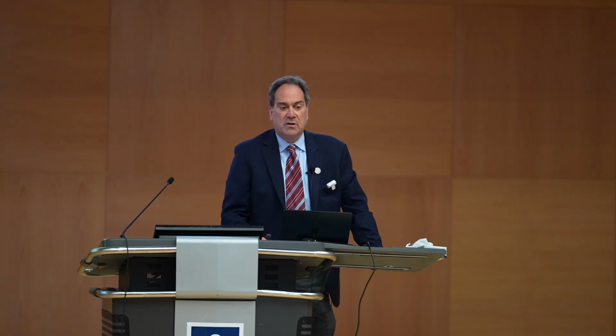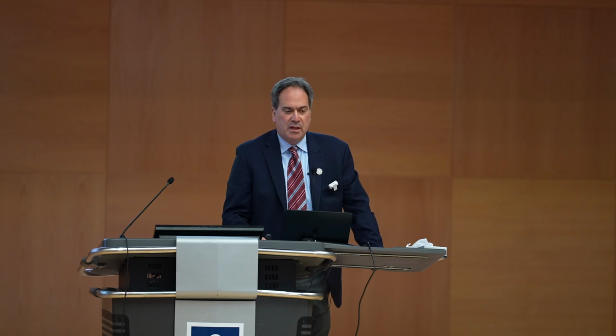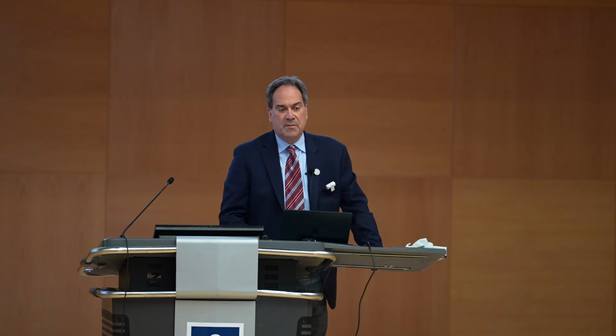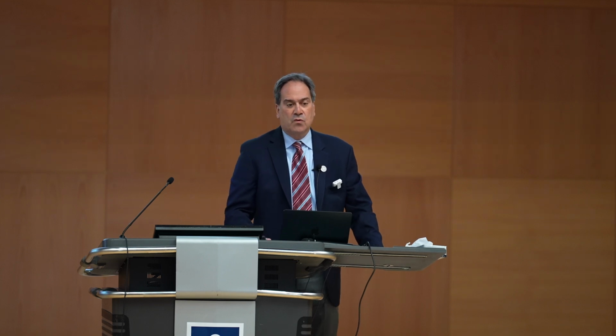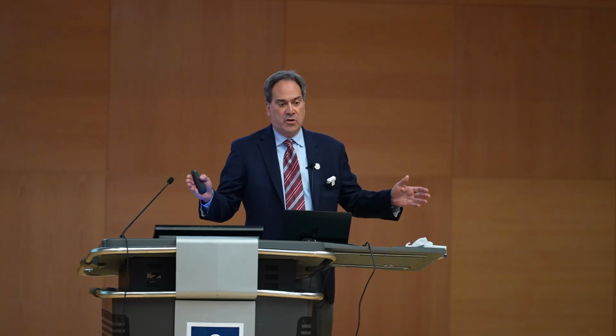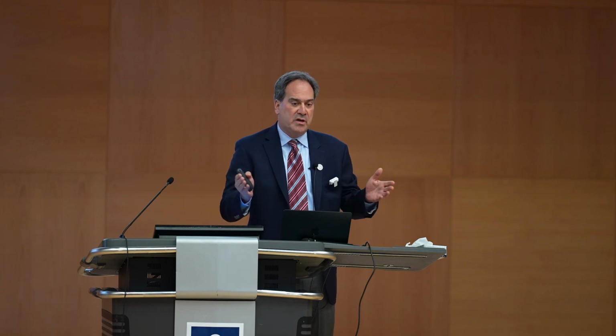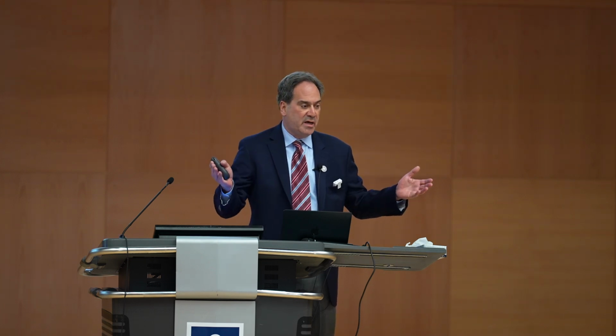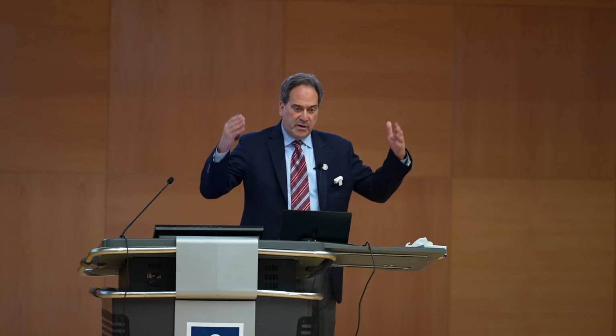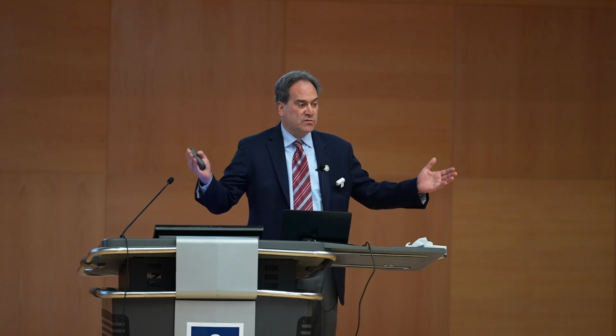At the same time, there was a pretty famous lab, George Whitesides', I think was also a King Faisal Prize winner in earlier days, developing something called micro-contact printing. And a lot of people thought these were competitive tools at the time. They're not, actually. They're highly complementary. Contact printing is a great way of printing in parallel over large areas. You can't go very small. You can go down to about 200 nanometers. We can go down to 10 nanometers. Very custom. Theirs is transfer one pattern, and that's what you get.